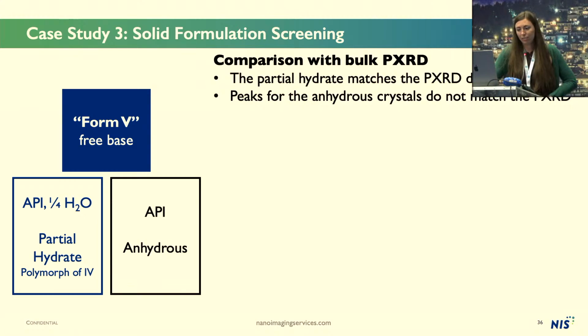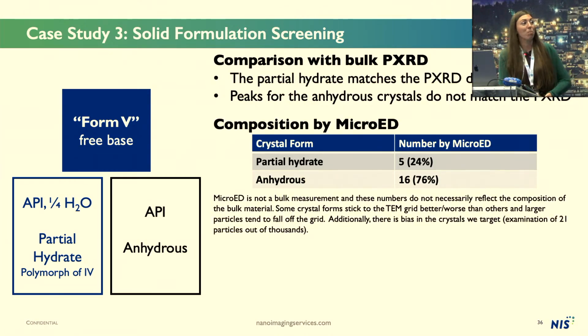Here's just for your information, the composition that we saw by micro-ED. So in the microscope, these crystals diffracted at very high resolution, so we only collected 21 data sets. 5 of those 21 were the partial hydrate, 16 were the anhydrous. So by micro-ED, you might conclude that this is mostly the anhydrous form, which it possibly is, but I add in this caveat that micro-ED is not a bulk measurement. We are only measuring data from a handful of crystals out of the thousands on this grid.